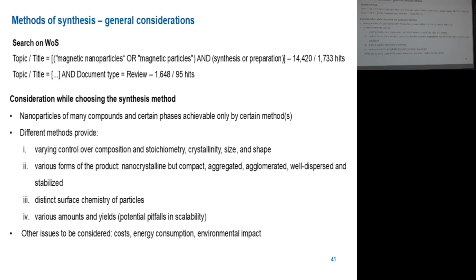Nevertheless, the different methods also provide the products in different forms. Maybe some experiments will lead to well-dispersed, isolated particles available in some suspension. In other methods, you will obtain just dry powder or some nanocrystalline material which is interconnected by sintering bridges, or which is glued, which is somehow compact. And this is also crucial. If you want to prepare some particles for magnetic particle imaging, you would prefer probably dispersed particles that can be easily and individually stabilized, rather than some compact piece of nanocrystalline matter.